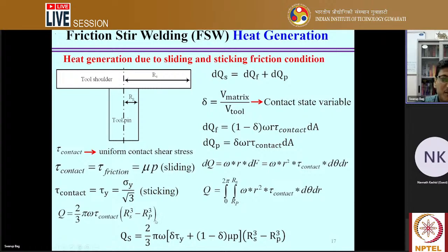Then we apply different contact friction laws. When there is sliding, we apply Coulomb's friction law, with the contact pressure P multiplied by the coefficient of friction. But sticking means the plasticized metal is exactly sticking with the workpiece. In that case you need to overcome the yield stress value, so sigma y by root 3, which is called the shear yield strength. The contact shear stress will be equivalent to the shear yield strength at the purely sticking condition. Combining these two, we can estimate the total heat generation in terms of the shoulder radius, the pin radius, the contact state variable, the pressure, the coefficient of friction and the rotation.